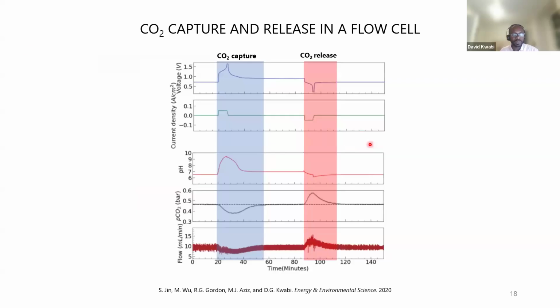So here's an example of some of the data we're able to generate. These are current and voltage traces from the electrochemical cell. You can see that as there's an increase in pH, or alkalization of the electrolyte, there's the CO2 capture, so we have a dip in our partial pressure of CO2. And then when we oxidize the electrolyte, there's a decrease in pH and an increase in partial pressure of CO2 as we release the inorganic carbon that was captured previously. So this is a proof of concept that got us very excited about the use of these systems for CO2 capture.